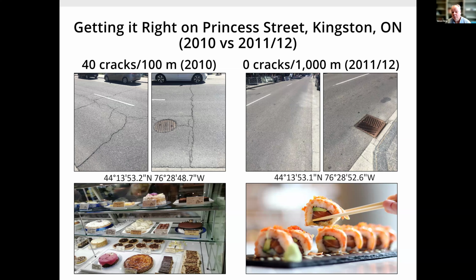On the right, we told the contractor we're going to test recovered asphalt binder and you're going to meet these criteria or you're going to be penalized. You're not going to get paid. Correct properties, correct acceptance criteria, recovered binder testing, virtually no distress for 7 blocks of Princess. Thank God we did this in 2011. If we stay the course and test recovered binder on enough mix samples, then we can do this. Everything should look like this in every municipality in Ontario.